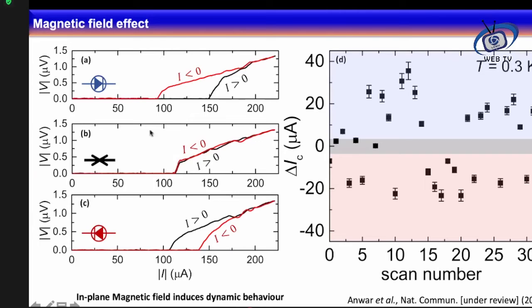And then if I continue to measure its IV curves, then it switched to the standard junction, meaning that the critical currents for both directions are the same, but it can also jump to the reverse biasing, meaning this time the negative critical current is higher than the positive critical current. And with this configuration, my device can jump between one of these three states. But if we look carefully here, most of the time it stays in the diode configuration for the forward biasing or the reverse biasing, and seldom does it go to the standard superconducting state.